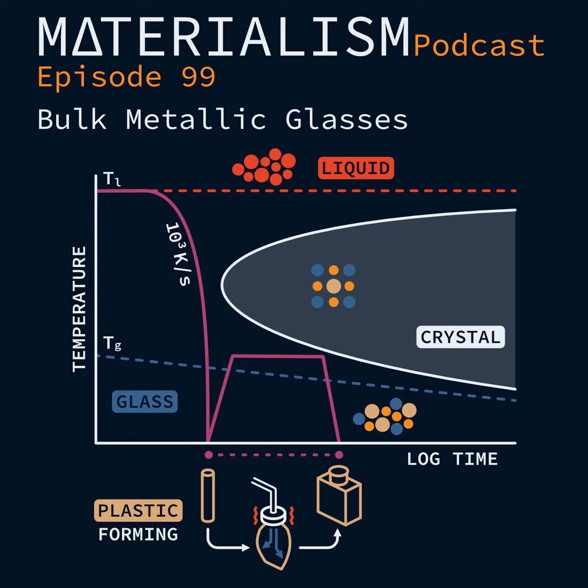Exactly. The first application of these bulk metallic glasses were golf clubs. People looked at this and said, this is what you want in a golf club. You want all the energy of the swing to be translated into the golf ball. And Liquidmetal Technologies made them. They were later also made in Japan. And then a year later, they were banned. Oh, really? So no longer allowed. They were too good. I believe it. The demos speak for themselves. They are only allowed to be used if you put an artificial damper on it, so then why bother? Exactly.